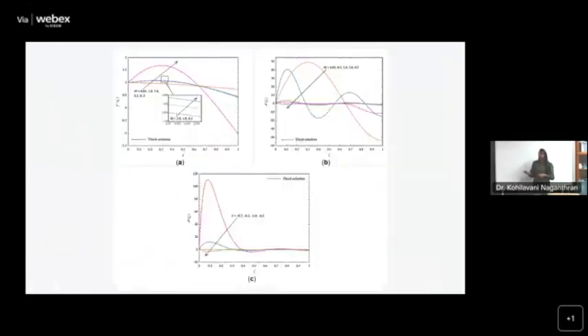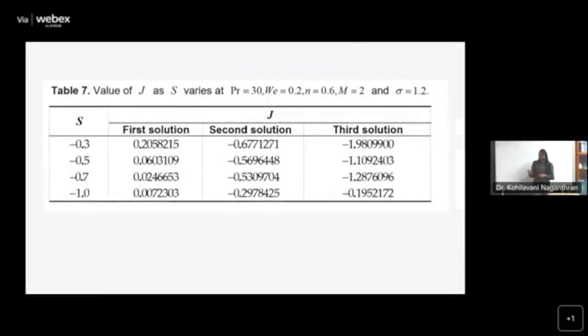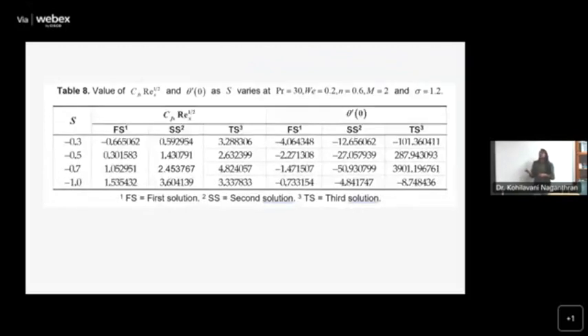Meanwhile, for the case of the injection, as the intensity of the injection increases, the film thickness reduces, and the skin friction coefficient increases, the drag force increases, and then the rate of heat transfer reduces. So you might ask me why I did not consider the suction. Because for the suction, I couldn't identify the second and also the third solution. It was quite difficult. So I just present all the values of the parameter where I can get the triple solution.